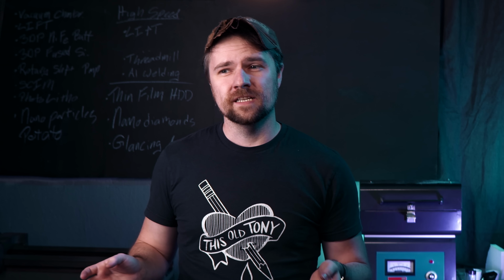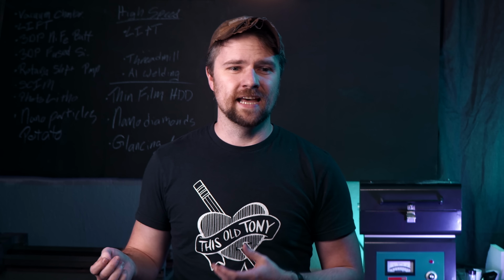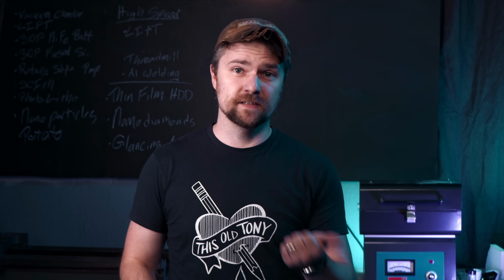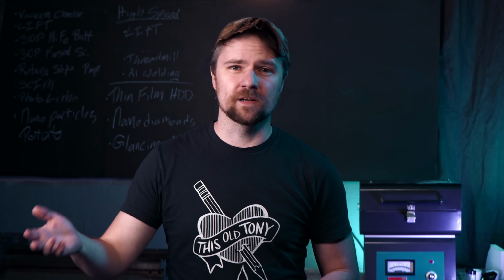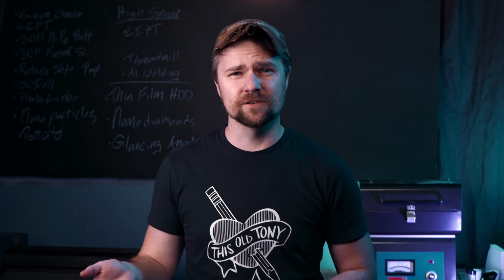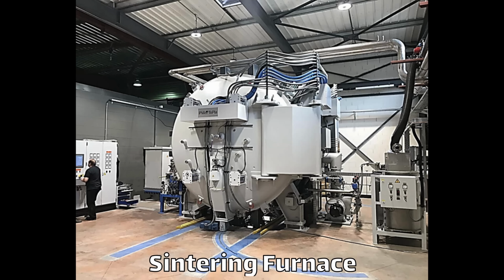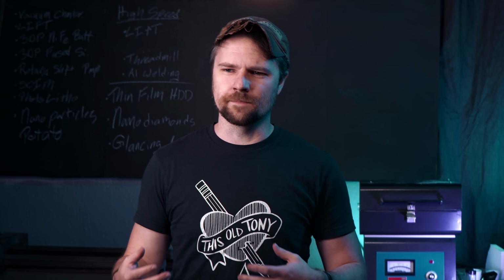Now, all these wonderful properties are also its big downfall, in that silicon carbide is just really hard to work with. It is physically hard, so it's difficult to machine. It's chemically inert, so you can't just dissolve it in some solution and precipitate it back out. And because of its temperature resistance, it's really difficult to sinter silicon carbide grains together. It requires in excess of 2000 degrees Celsius to do direct sintering, or you can do other schemes like reaction bonding, where you melt liquid silicon to infiltrate in between the silicon carbide grains, also at really elevated temperatures. So all the ways to actually process this material are extreme, which limits its use just because it's so difficult to make parts out of it.